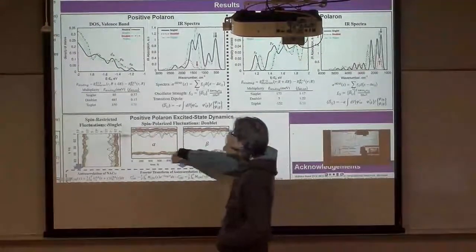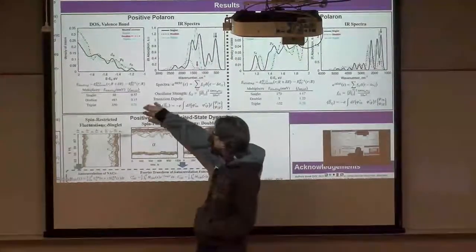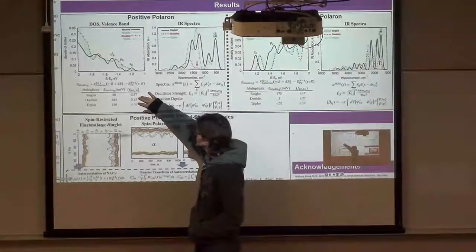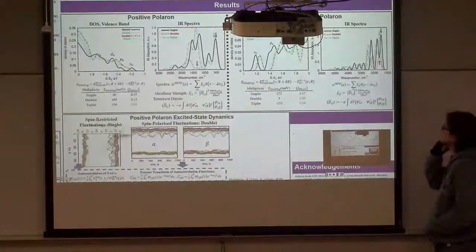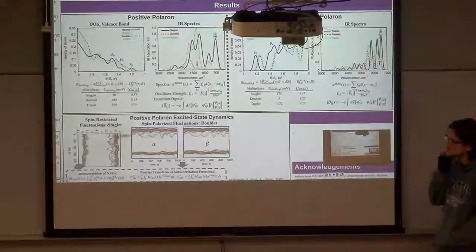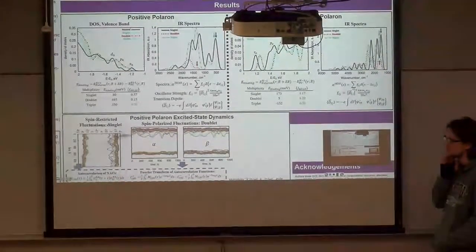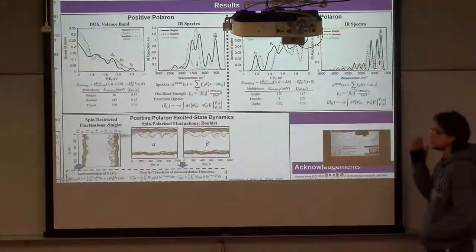I'll just mention the oscillator strength. The color codes here correspond to the arrows in the spectra figures. The numbers don't mean much, but they're moderate compared to the negative polaron for the other model that we have. There is no reason to compare to the neutral reference state, because it doesn't absorb in this range. If you have no polaron intrinsic to the system, it will start absorbing at about 15,000 inverse centimeters. And then same deal with the negative polaron.